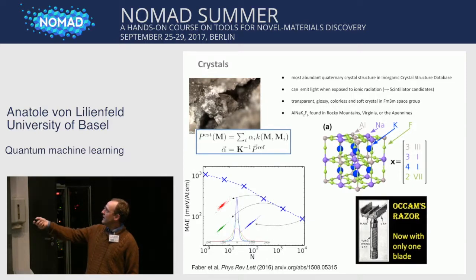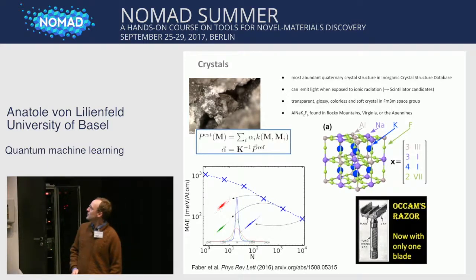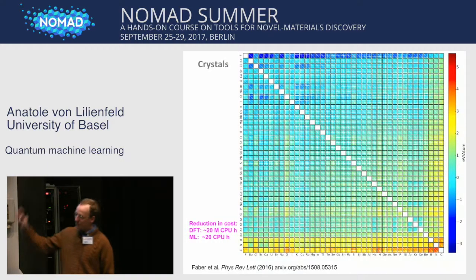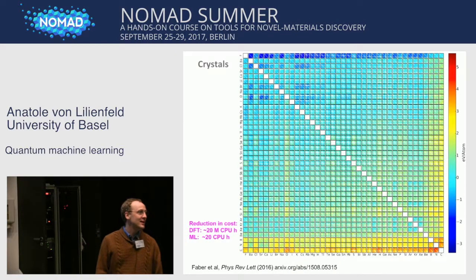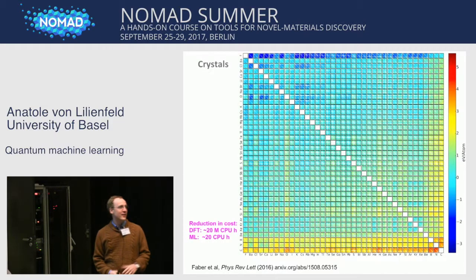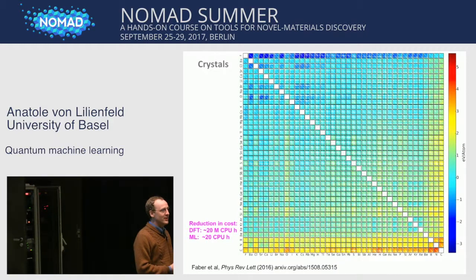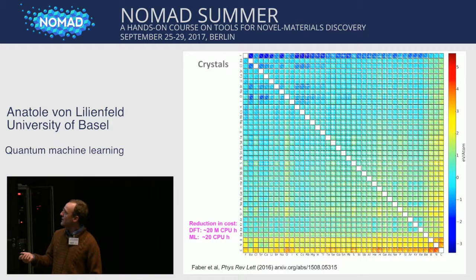This is the out of sample prediction error coming down on this log-log curve for the formation energy. And we reach 100 meV per atom after training on 10,000 elpasolites. And then, of course, you can turn around and screen all possible elpasolites. In our case, there were 2 million elpasolites, so you're looking at 2 million energy estimates with an expected accuracy of what DFT would usually give you, so roughly 0.1 eV per atom.